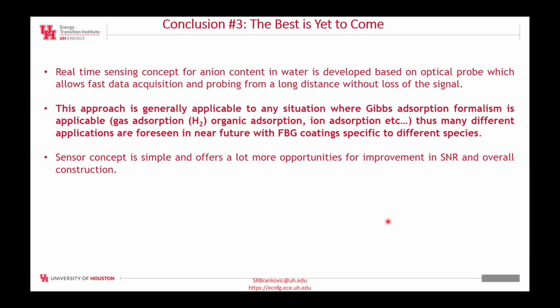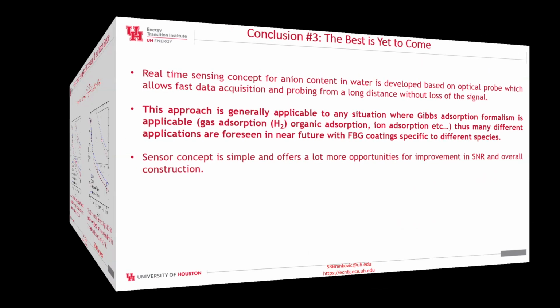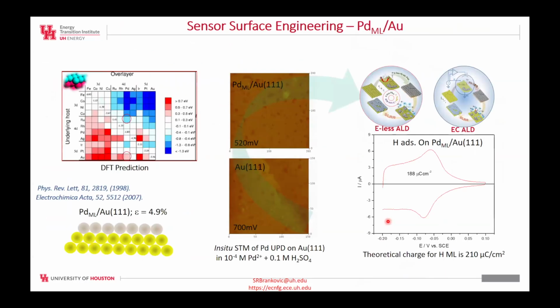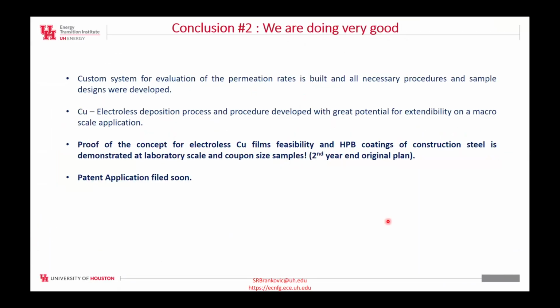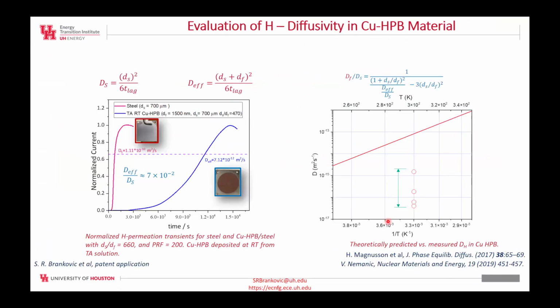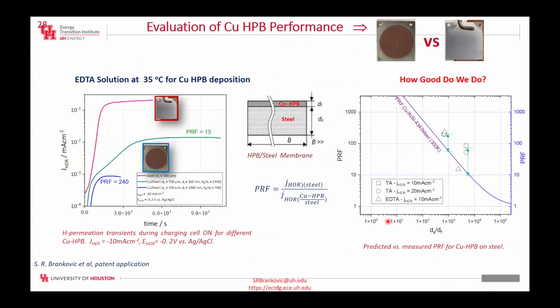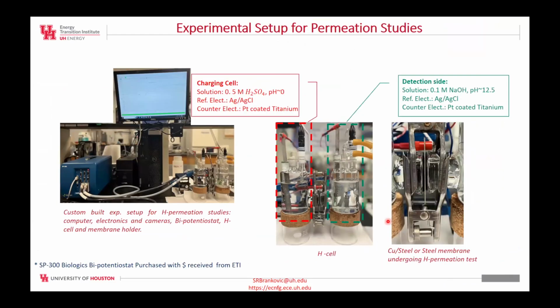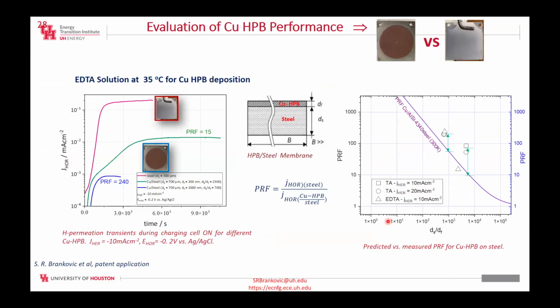Thanks for the presentation. The question is on the copper layer on the pipelines. The pipelines are going to be exposed to ambient conditions, I can imagine from freezing temperatures to 100 degrees Fahrenheit. The question is, if there is a differential thermal expansion between the steel and the copper, how robust would our copper layer be to the hydrogen? Would it allow some places for hydrogen to go through and attack the steel, as the materials expand differentially with temperature?